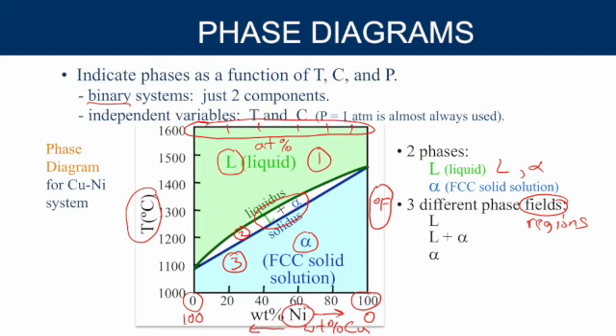So what's going on here? It's got some interesting information we can get. My first question to you would be, what is the melting point of pure nickel? This is something you could easily get off of this graph. You could also get the melting point of pure copper, as well as the melting point of any mixture of the two. So pure nickel would be 100 weight percent nickel. We go over. Looks like the melting point of pure nickel is right about 1450 degrees Celsius.